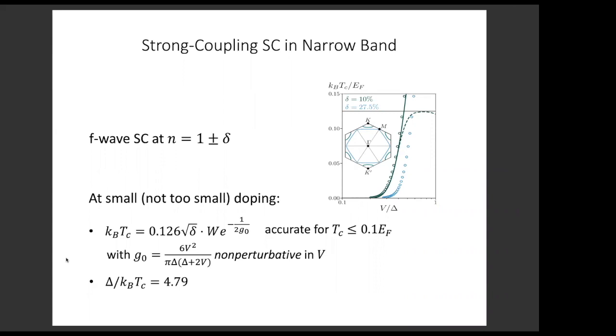In particular, at small doping, we have an analytical result for the Tc that is shown here. Tc is proportional to the square root of the doping density delta, and it depends exponentially on this coupling constant G0. The expression for G0 is shown here. It depends on the bare repulsion V and on the bare gap delta. So the expression for G0 is non-perturbative in interaction strength. And this formula for Tc holds at small doping and is accurate up to Tc around 0.1 Fermi energy, EF.